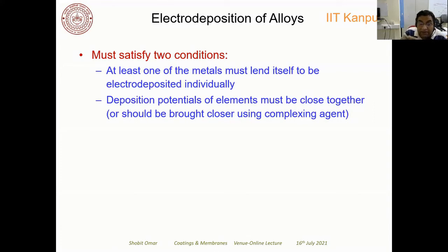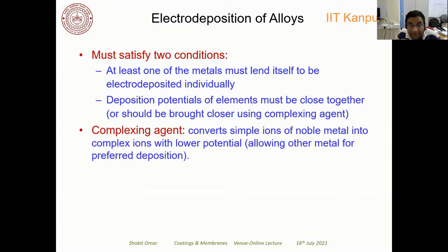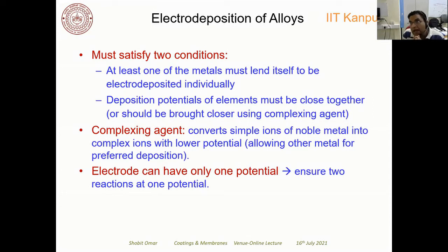And if there is a difference between the potentials, we normally use a complexing agent to lower the potential of the element which has a higher potential. A complexing agent is normally used to convert the simple ions of the metal into a complex ion with lower potential, so that the potentials of both ions are very close to each other, and then they can deposit at the same potential. Remember, an electrode will have only one potential, and you have to deposit two ions which have different potentials, right? So of course, the ion which has a higher potential will deposit, but then you can reduce that potential using the complexing agent. So this is the idea that people normally use to electrochemically deposit alloys.